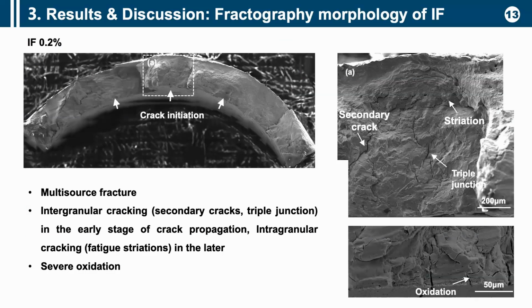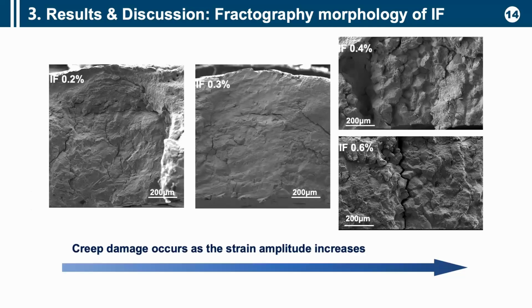For the fractograph morphology of IF, the observation shows multi-source fracture and intergranular cracking. You can find secondary cracks and triple junctions in the early stage of crack propagation, and intragranular cracking in the later stage. And we also find some thorough oxidation here. If we compare the different strain ranges for IF loading, it seems creep deformation and creep damage increase as the strain amplitude increases.